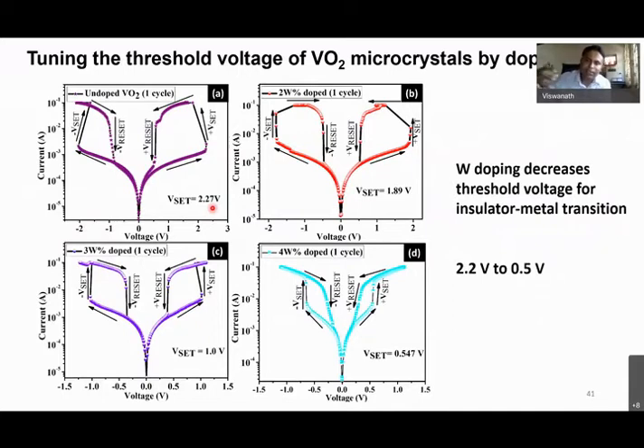Again, tungsten being the heavier atom, it will actually induce compression in the lattice. So that is something not probably new, but what I would say is new is we have also shown by doping how you can change the threshold voltage when you trigger the phase transformation electrically. So that is what's shown here.